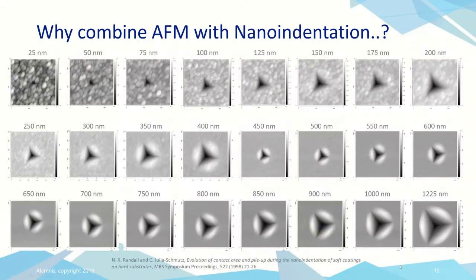Now, if we want to investigate, for example, a coating, then we can make indents at various depths. So here we see a titanium coating on silicon. So we've made indents from 25 nanometers depth up to 1.2 microns, okay? And the coating thickness here is about 300 nanometers. So at the very shallow depths, we're only measuring the coating properties. As we go deeper, we start to have the influence of the substrate. And around 300 nanometers, we're actually into the substrate.